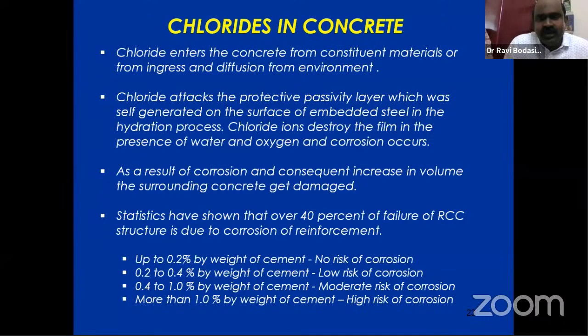Coming after sulfate, these are the twins which cause concrete to deteriorate at a faster pace. One is sulfate and the second one is chlorides. Chloride enters the concrete from constituent materials, and from ingress and diffusion from the environment. The chloride attacks the protective passive layer, which is self-generated on the surface of the steel in the hydration process. Hydration is when water, H2O, comes in contact with cement, and immediately the exothermic reaction starts, forming the cement paste. That layer forms over the steel. As a result of corrosion, the increase in volume damages the surrounding concrete.